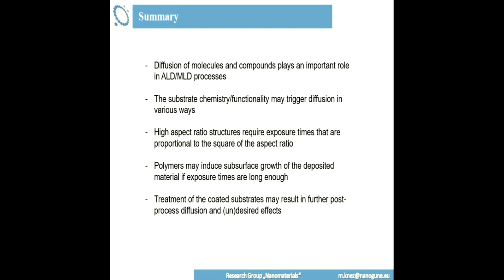Polymers, I think this is also very important. Polymers are able to absorb much of your precursor. They will just dissolve it. And if you don't want to have it, you need to take the appropriate measures. If you don't take those measures and you did not expect infiltration into your polymer, don't be astonished that your polymer changes all its properties. So all the infiltration work which was done so far led to mechanically altered polymers.